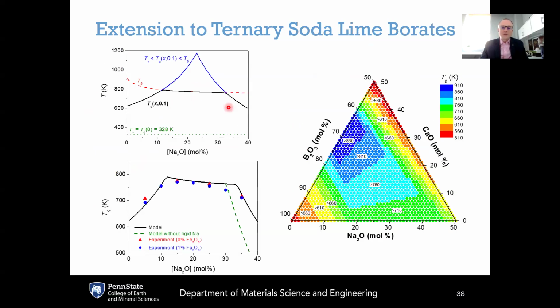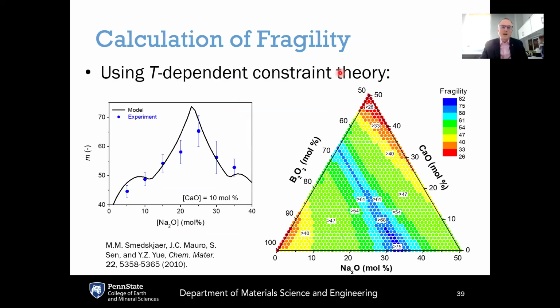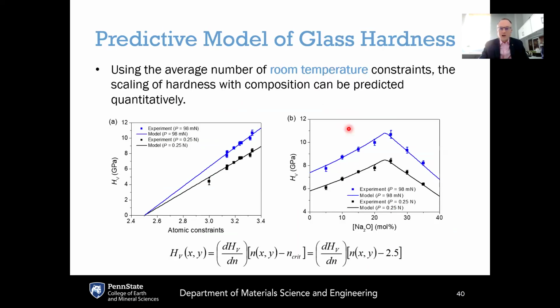And it's not just glass transition temperature, too. For binary systems, it can easily be extended to ternary systems. This shows how the Tg evolves for soda-lime borate. So this is a sodium-calcium borate system. It can be extended to get other properties like Angell's fragility index. This shows the evolution of fragility index in soda-lime borate systems. It can predict mechanical properties here.